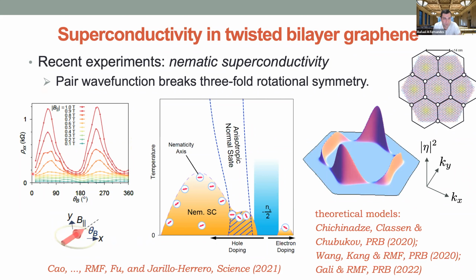What they saw, surprisingly, was a very strong twofold signal, which is very odd given the fact that, as you can see, this lattice has 6-fold, not twofold, symmetry.